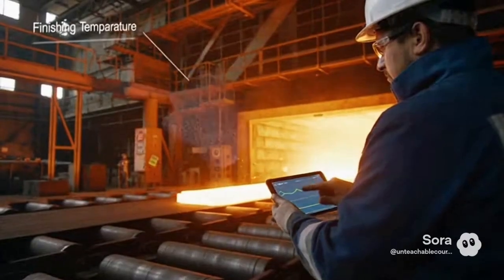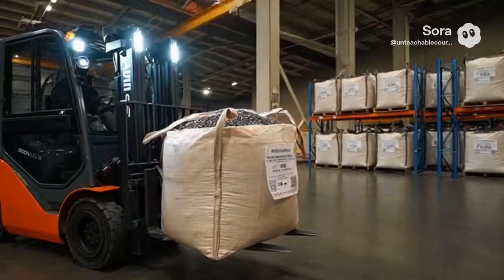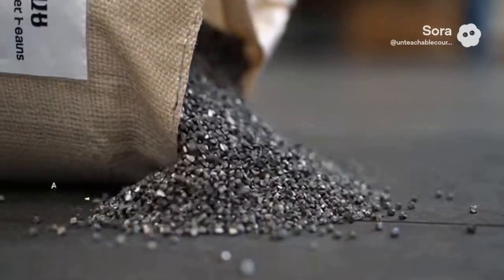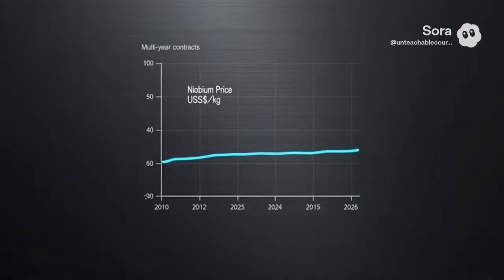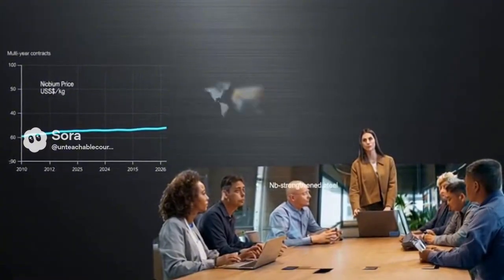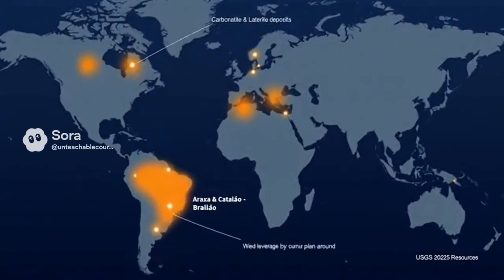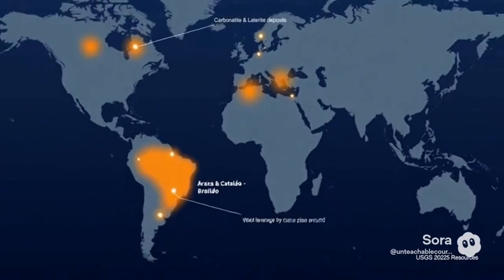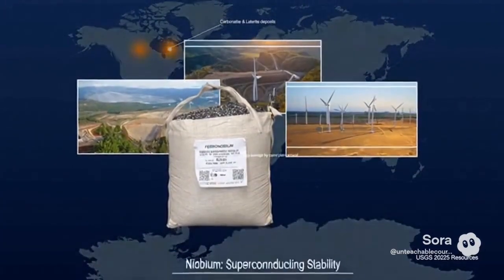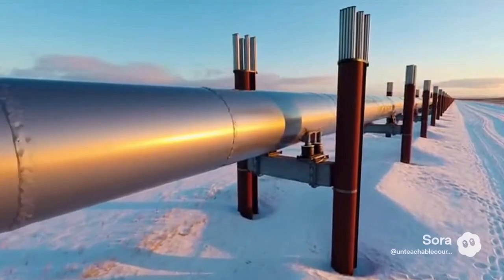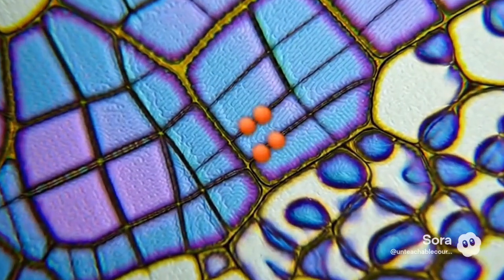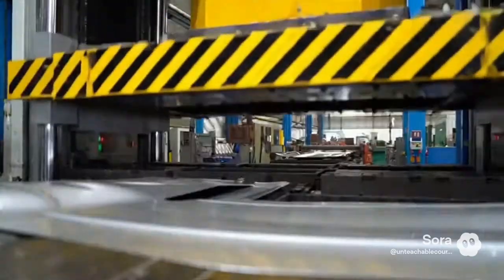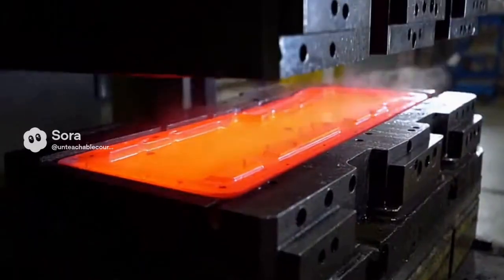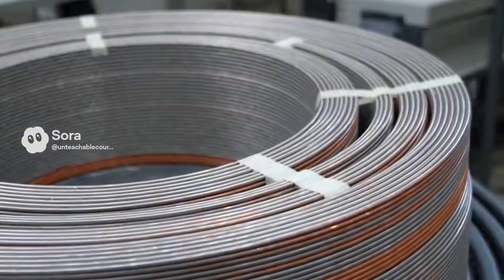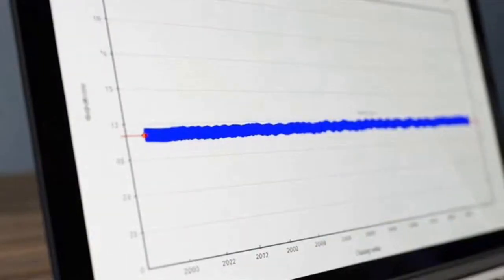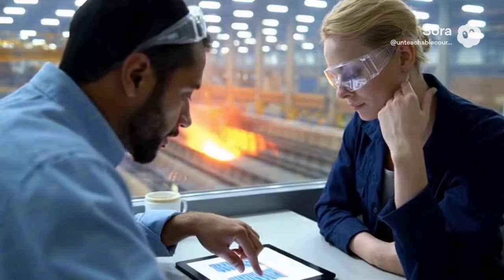If you trace that contract down the value chain, you discover how much of niobium's value is really variance management in disguise. The alloy arrives in bags or drums, usually in a composition around 60% niobium by weight with iron as the balance and impurities carefully policed. Mills meter it into the melt late, just ahead of tundish and mold, because the whole point is to have niobium sitting in solid solution in austenite when the real work begins. The addition practice is a ritual because hitting solution content without overshooting is the difference between a sweet spot precipitation of niobium carbide and niobium nitride during cooling and a cranky microstructure that refuses to land inside the property window. The bag does not look like leverage. In practice it is process control poured from a forklift.